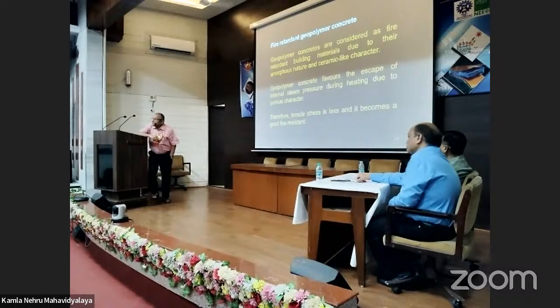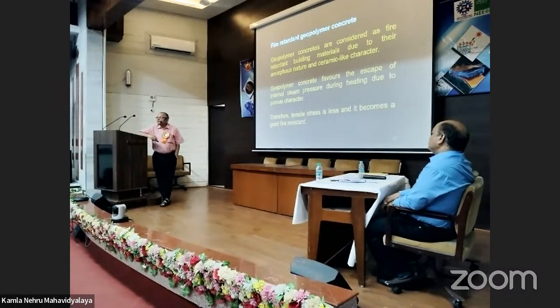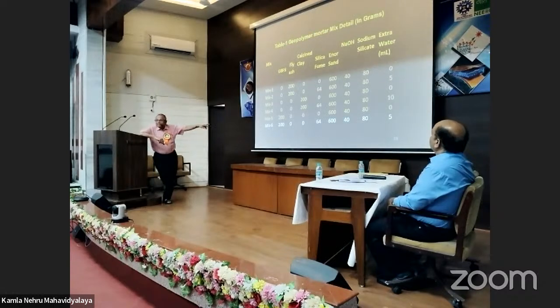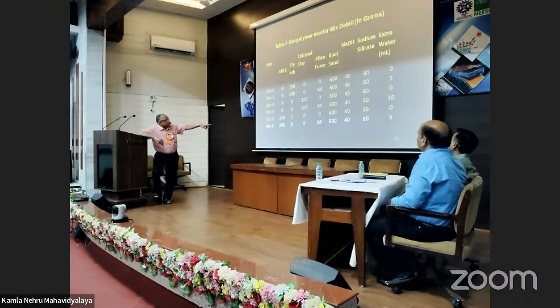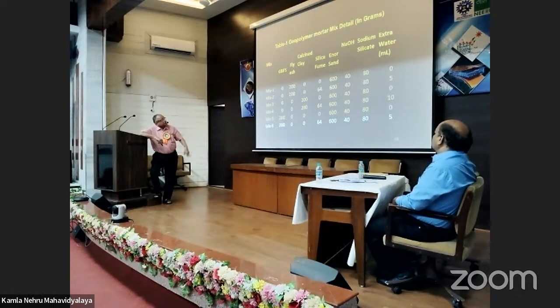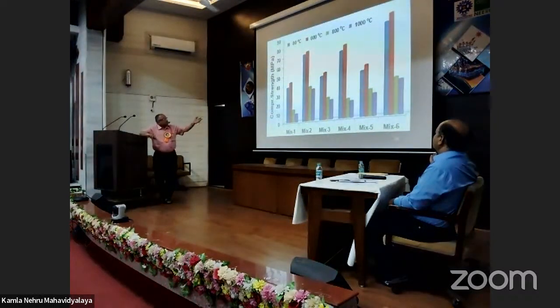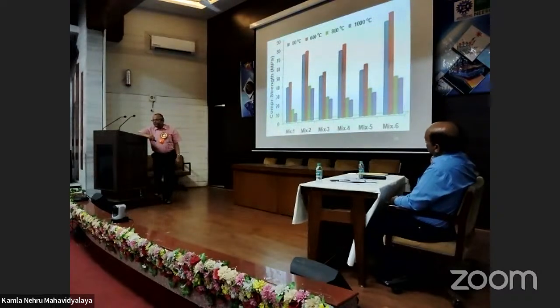Now, these geopolymer cements have very high compressive strength. They are much better than normal Portland cement in one respect, but there are certain drawbacks which I will discuss later. One of the most advantageous features is fire retardant geopolymer concrete. Here you see that we have made different mixtures in our laboratory. Mixture number 6: granulated blast furnace slag 600 grams, mixed with silica fume 64 grams, sand, sodium hydroxide, sodium silicate, and extra water. When we heated it at 80 degrees centigrade for 24 hours, we determined the strength of this mortar at different temperatures.